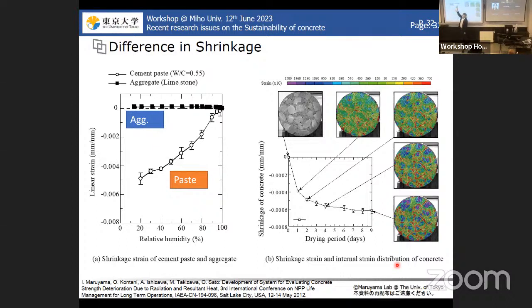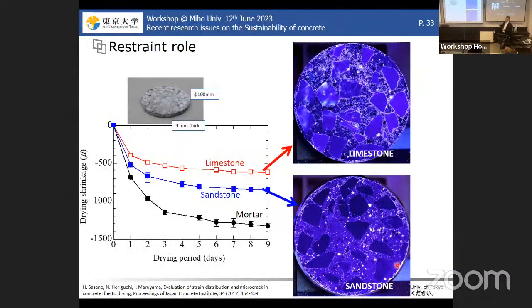But when we use the limestone, the shrinkage is almost zero, meaning that there is a volume mismatch between the aggregate and the cement paste. So we should see some discrepancy. It produces cracks inside. Therefore, around the aggregate, we generally see shrinkage-induced cracks and fine cracks, which can be confirmed by the digital image correlation method. And if we use the limestone, the non-shrinkable one, this kind of cracks are distributed like this. But in the case of the shrinkable aggregate, the damage is mitigated.